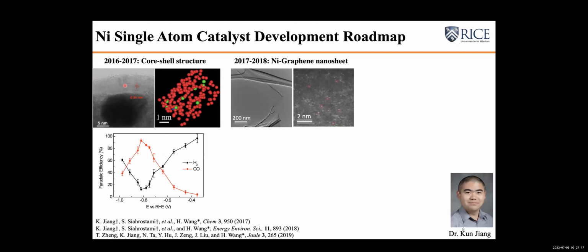If that's the case, we can just get rid of these nickel nanoparticles because they are not participating in the reaction. So why don't we start with graphene nanosheets, where you can dig a lot of holes before you incorporate some of the nickel dopants inside and then do thermal annealing? Because of the very strong formation energy, you can automatically suck those nickel atoms into the defects, making those nicely isolated nickel single atomic sites on the graphene nanosheet.